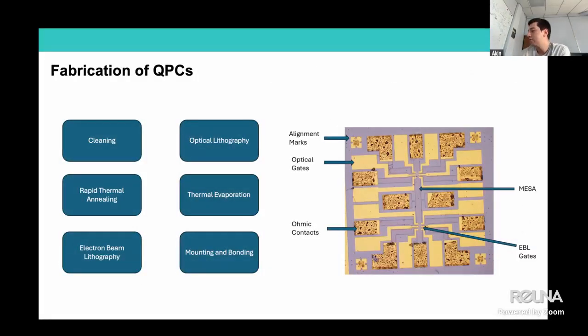In the fabrication of these devices, it's quite generic steps. A grower will grow the wafer with the MBE process, and then an experimentalist or fabricator will receive it. This wafer needs to be cleaned, and then there will be optical lithography to create a mesa structure where the 2DEG is selective. Around that mesa, you can see there's a Hall bar here, so there are different parts. These are all 2DEG, and outside of this region you don't have 2DEG, so there are no conduction electrons here.